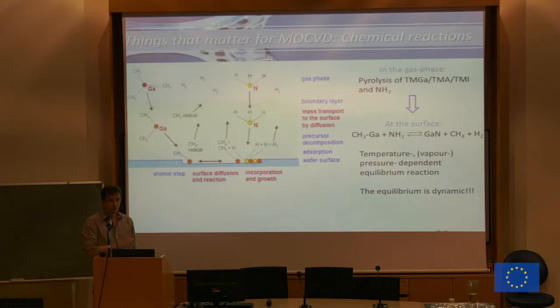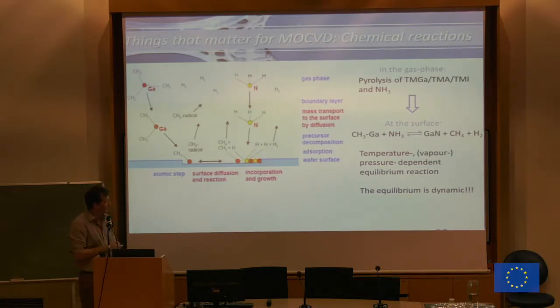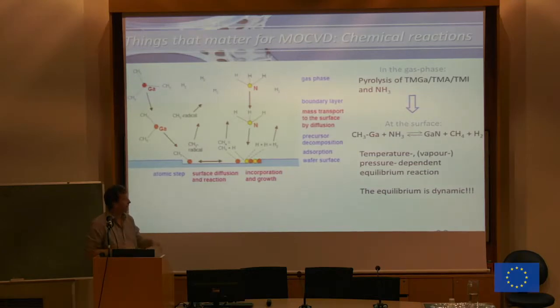So you can push it either way. You can go from gallium nitride this way, or you can go from the gas phase that way, just depending on how you control the thermodynamics of your reactor. So it is not a given, it's really an equilibrium reaction. And of course, we will control the direction of this process by controlling temperature, pressure, and especially the vapor pressures of the sources.